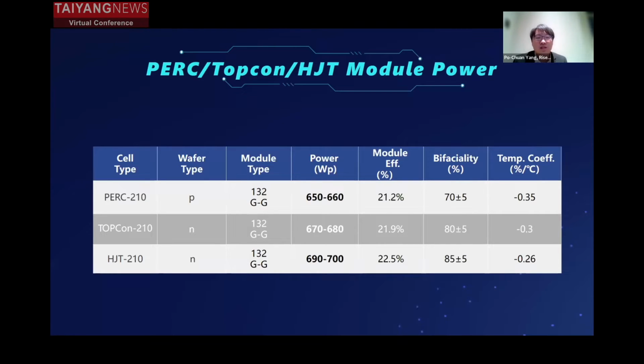So in this case, we can find that TOPCon module is higher than PERC module, roughly 15 to 20 watt, and heterojunction is higher than TOPCon, roughly 20 to 30 watt. Considering the bifaciality, TOPCon is roughly 80% plus or minus 5%, and heterojunction is 85% plus or minus 5%. And the last one is the temperature coefficient. Heterojunction has the lowest temperature coefficient, so it can have better power output in real conditions.